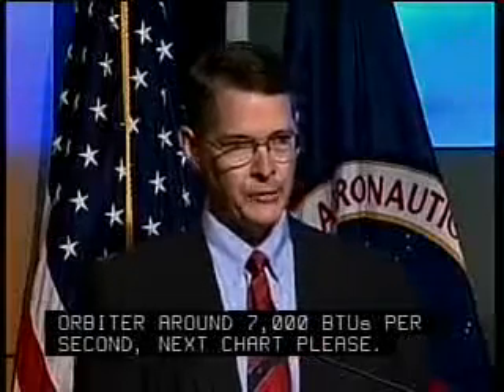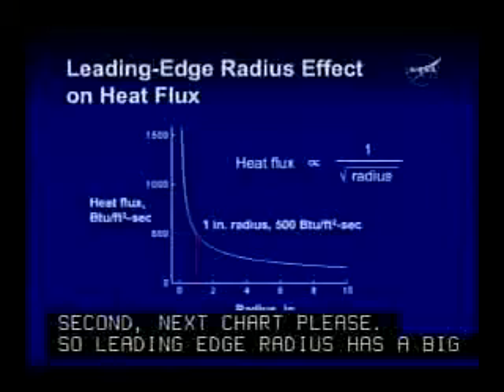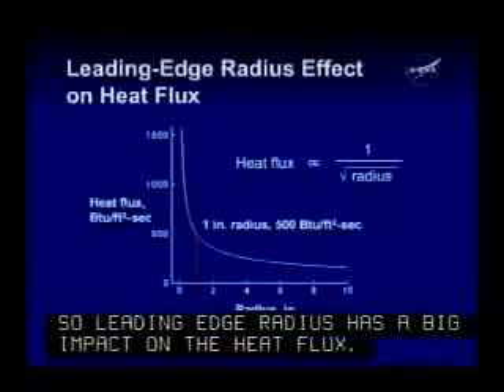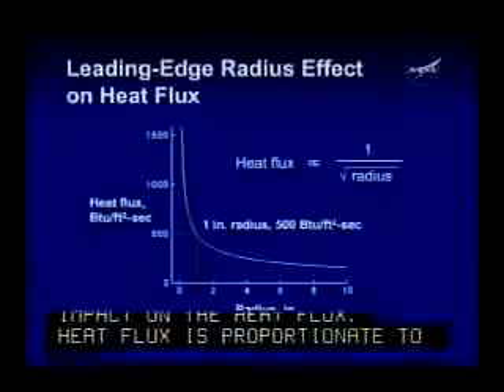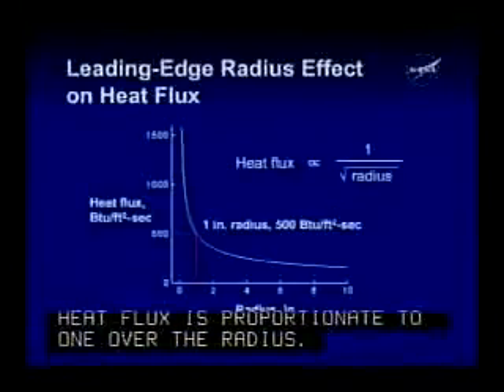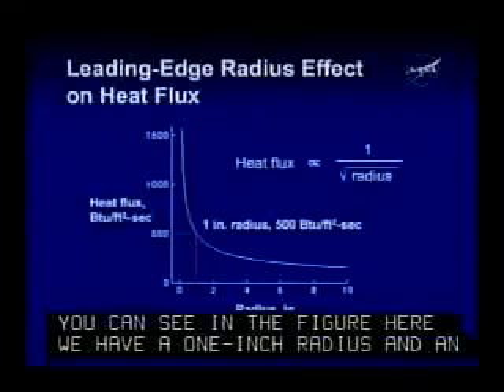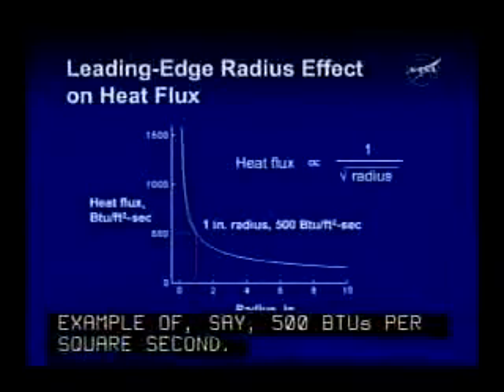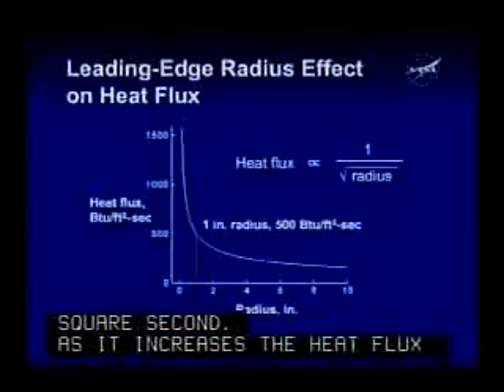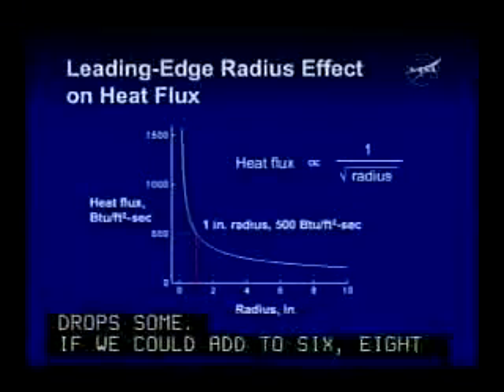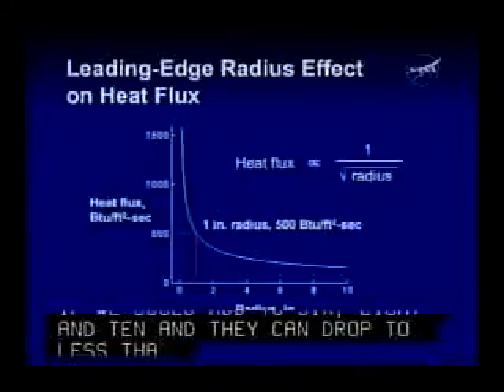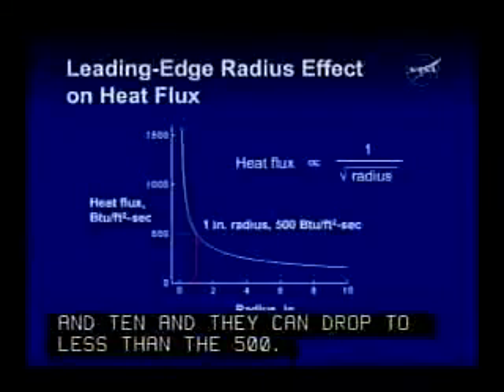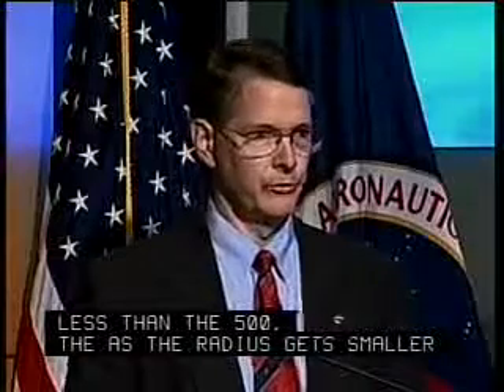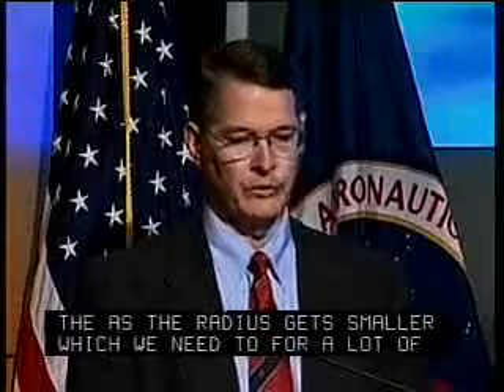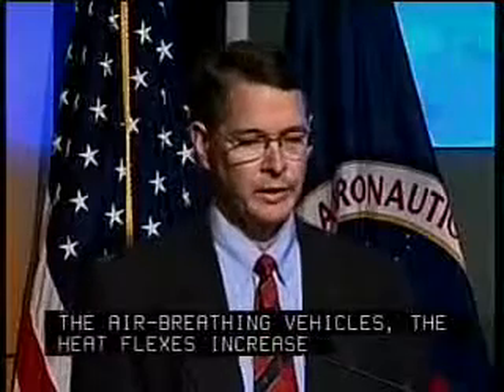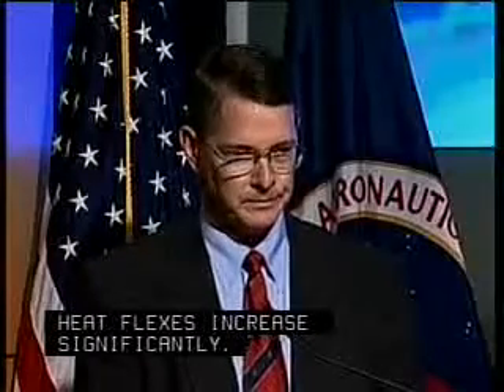Okay, so leading edge radius has a big impact on the heat flux. Heat flux is proportional to 1 over the radius. You can see in the figure here, we have a 1-inch radius and, as an example, let's say 500 BTU per foot squared second. As the radius increases, the heat flux drops some. As we get out to 6, 8, 10-inch radius, heat flux drops to, say, half and even less than the 500. However, as the radius gets smaller, which we need for a lot of the air-breathing vehicles, the heat fluxes increase significantly. Next chart, please.